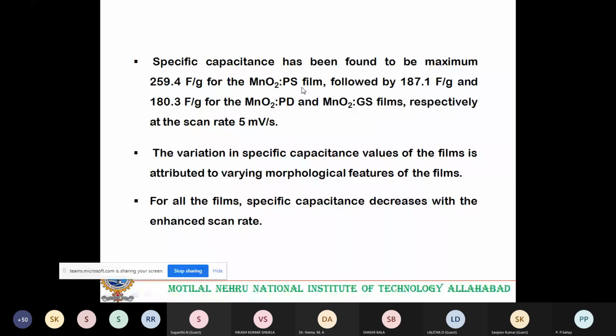Why does this variation occur? The variation in specific capacitance value of the films is attributed to varying morphological features of the films, because from the SEM and AFM we have seen that the morphology of the films is different, because the morphology of the films is influenced by the deposition mode. For all the films, the specific capacitance decreases with the enhanced scan rate. Naturally, if the scan rate is fast, the ions will not get sufficient time to intercalate into the film. That is the reason all the films' specific capacitance decreases with the enhanced scan rate. Okay, so these are the inferences drawn from the cyclic voltammetric study.